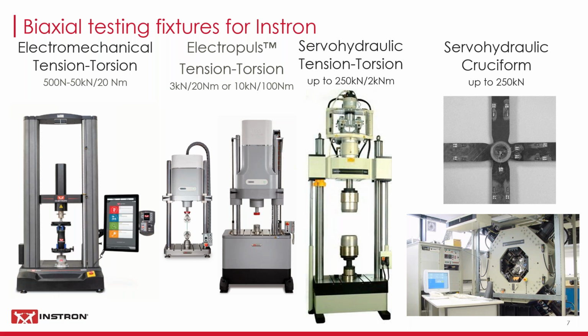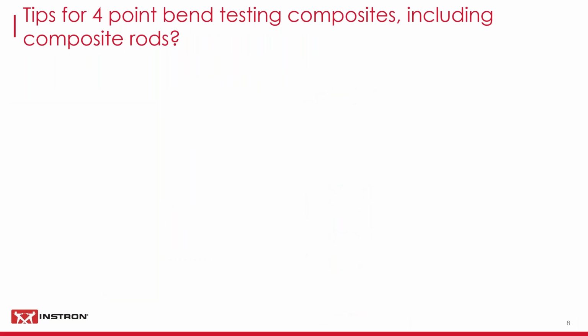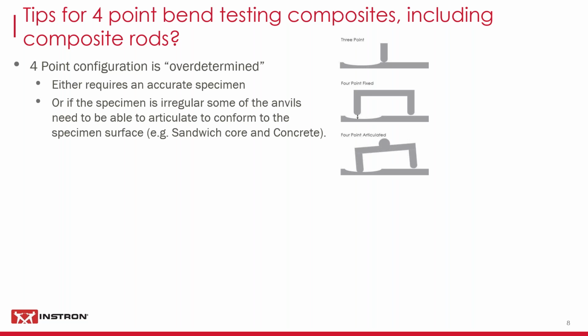Okay, I'll move on to 4-point bend testing of composites, including composite rods. I'll first say a couple of things about 4-point bend testing. Well, one thing to say is that a 4-point bend configuration is actually overdetermined, so it's overconstrained, and that it requires an accurate specimen. If all the anvils are to contact the specimen at the same time, with the same